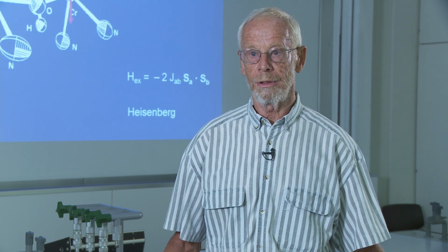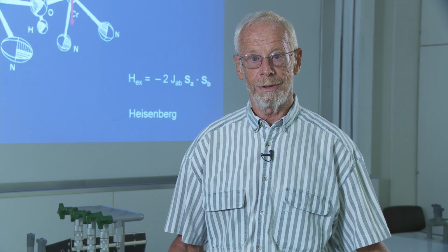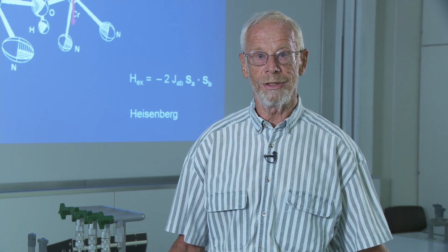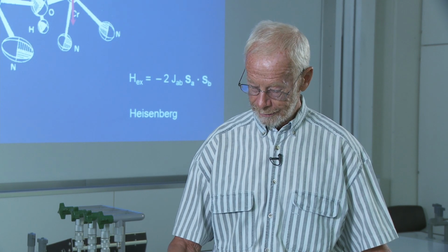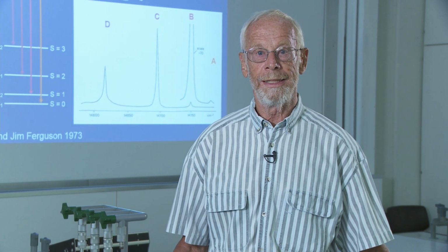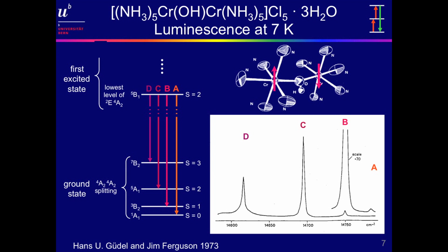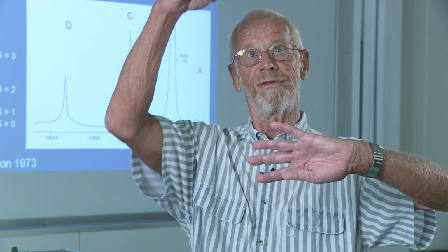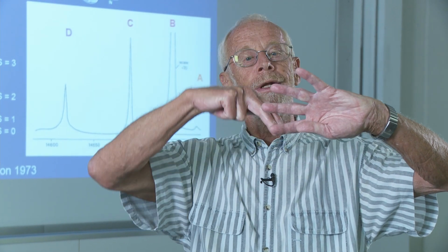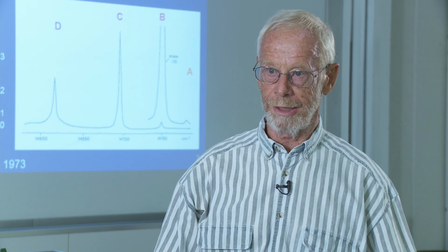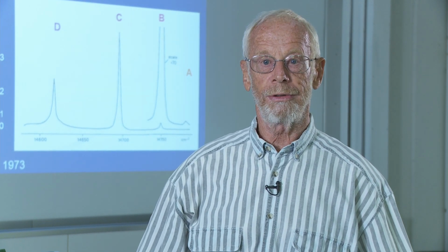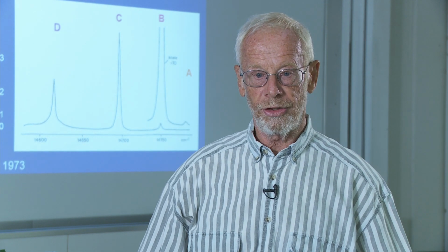Now the exchange splits all the energy levels of the single ion chromium, and our aim was to directly measure these splittings by spectroscopy. And it worked. Here on the right you see, again in the region of R lines, 4 distinct electronic lines, and they can be readily assigned, as shown on the left, to transitions from the emitting state to the 4 levels of the ground state. And from these splittings, both in the ground state and the excited state, we gained considerable insight into the nature of the coupling.